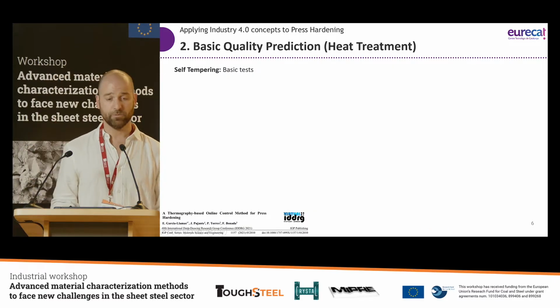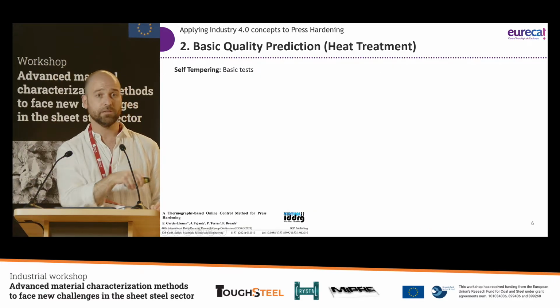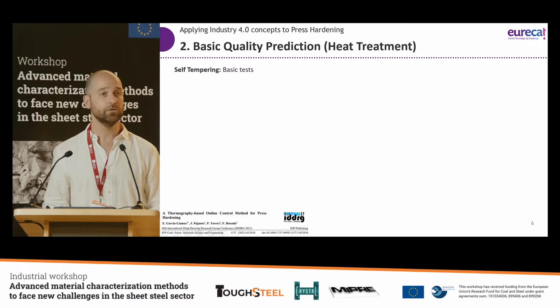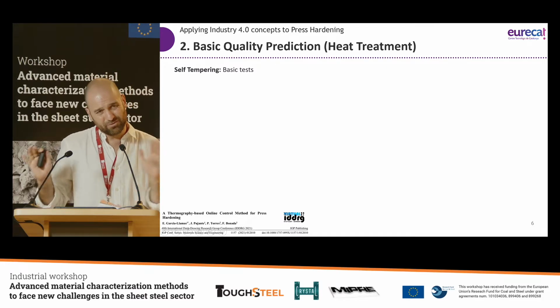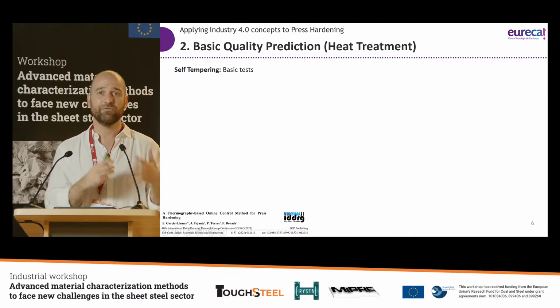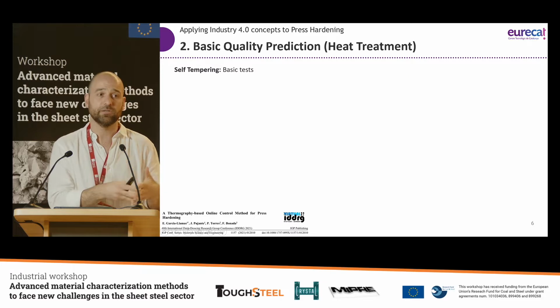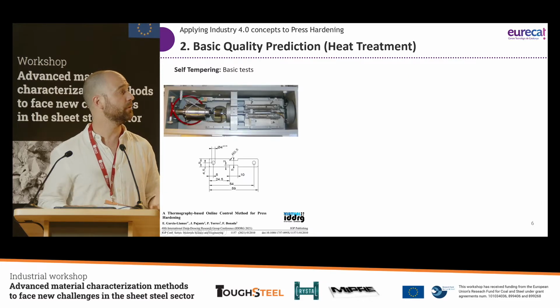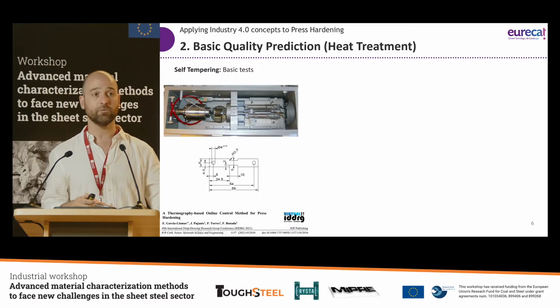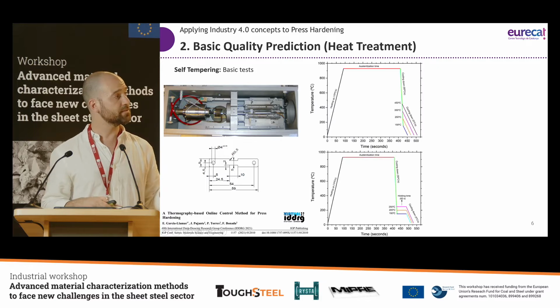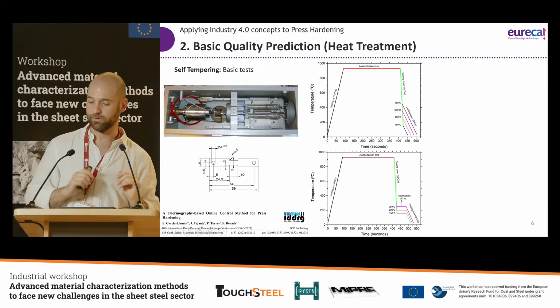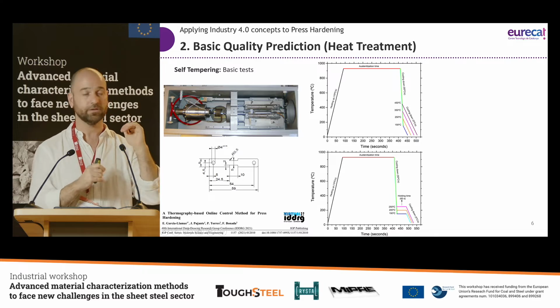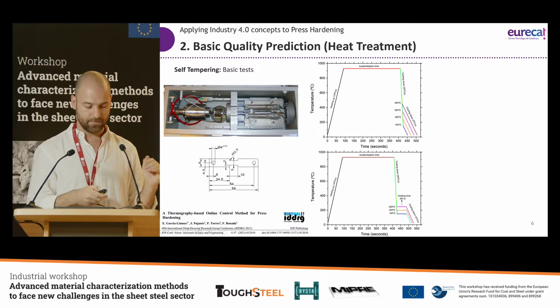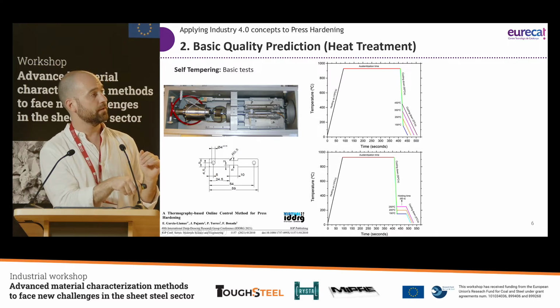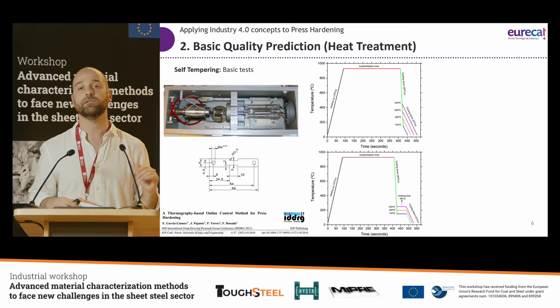Self-tempering, basic test. In this paper that we published a couple of years ago, we wanted to study, in a somewhat rudimentary way, what self-tempering is and how it can affect the final mechanical properties of a hot stamped component. We took a dilatometer and started forcing cycle times that would look something like self-tempering in this case. So we have a die that opens before time, and a component that exits the die too hot: 400, 300, 200, 150 degrees, something like that.